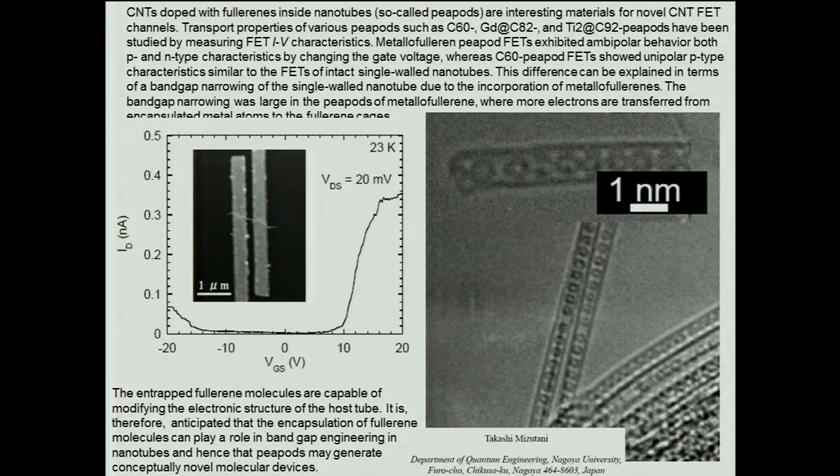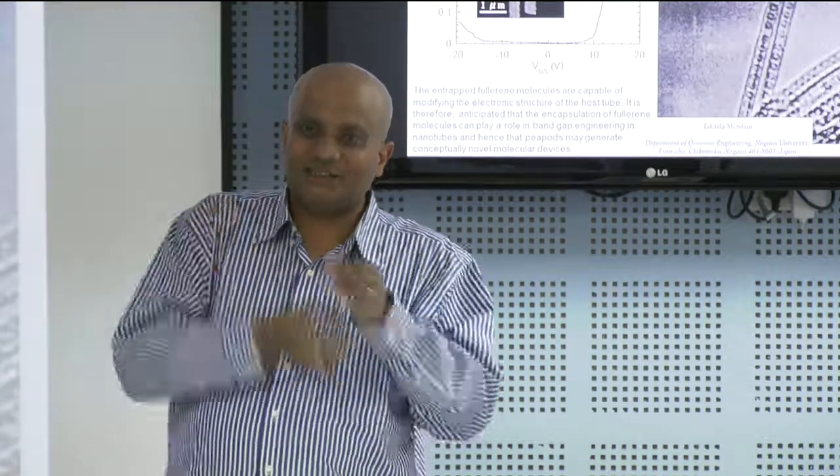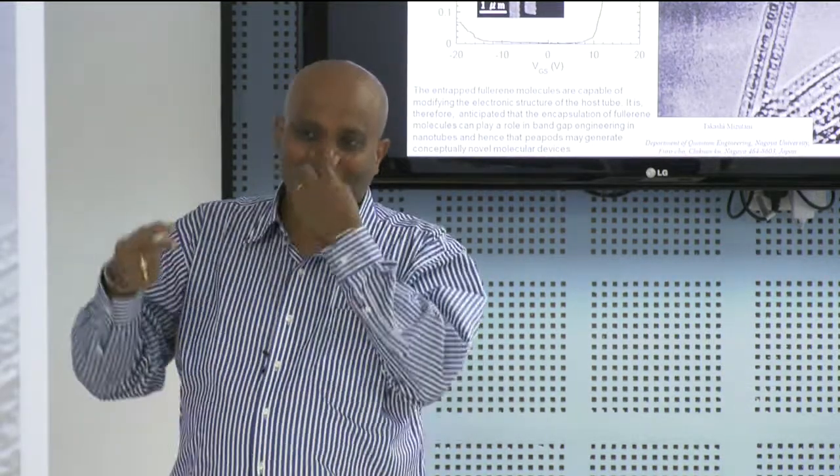So you have to have some conducting material over there in the source, and it should be sticking over there. One of the reasons why most of these results have come out from only a few groups is because they have the technique of making good contact. If you put the carbon nanotube between the source and the drain it is fine, but it does not guarantee that it is going to be a transistor, because there might be a big insulation between the source and the nanotube and the drain and the nanotube.